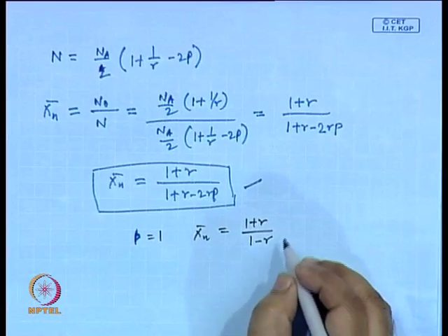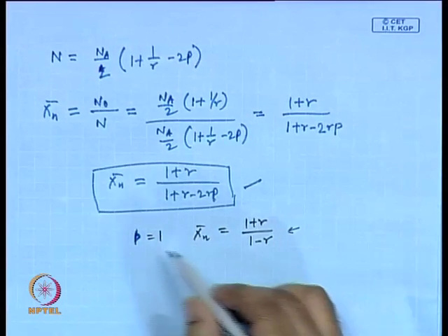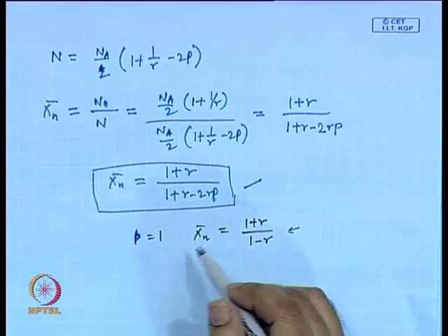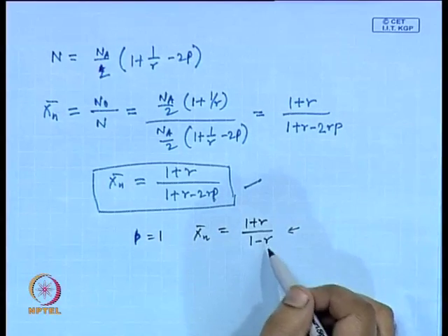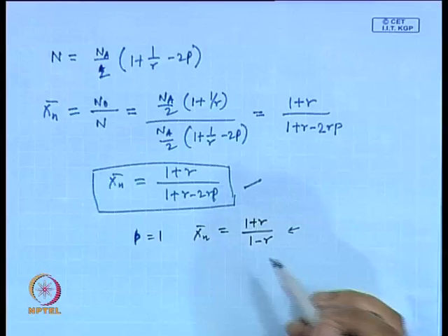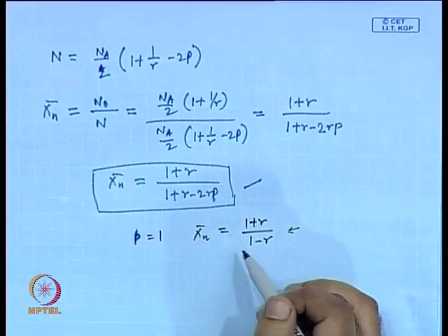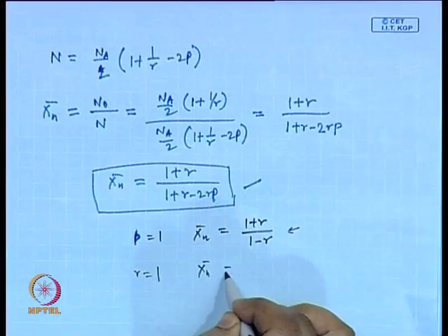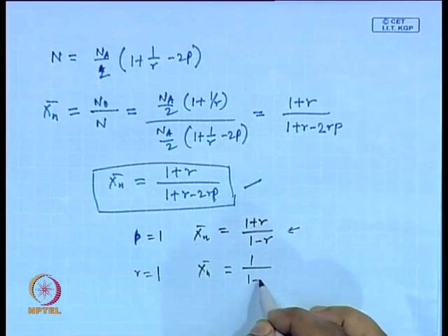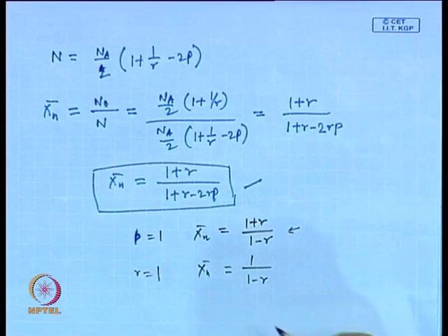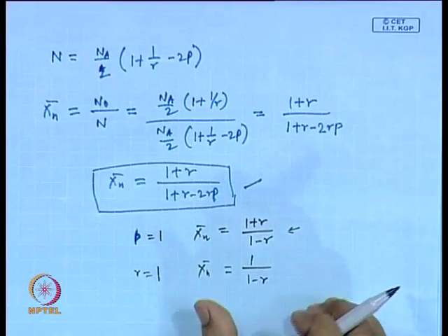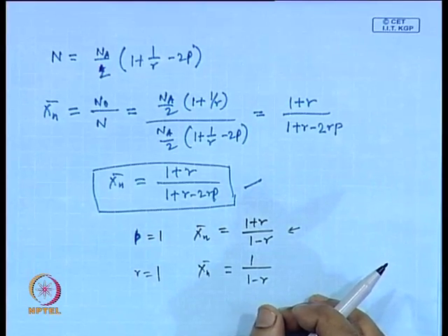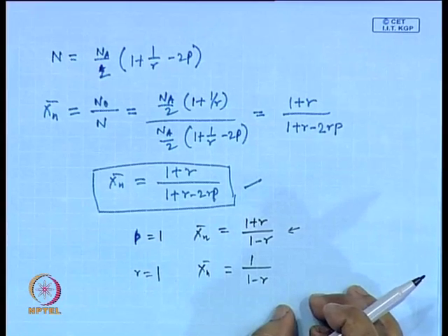This is typically done: you do your reaction as best you can, hope that P is close to 1, and choose R at the beginning so that you can target x n accordingly. And in the case where R is 1, x n gives us back the original Carothers equation, where we started with a 1:1 ratio of the two bifunctional groups.